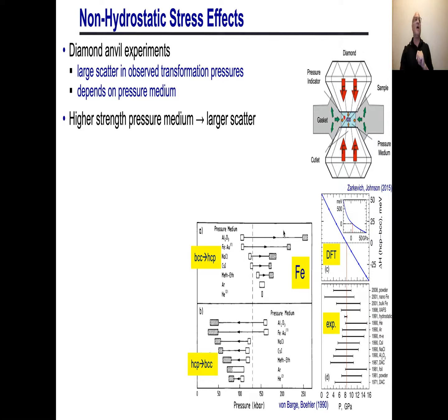Now, if you do a DFT calculation, this is for iron, and this is from some work by Johnson, you get a transformation pressure of 9.56 GPa, which is reasonable. So just to get kilobars to gigapascals, it's a factor of 10.